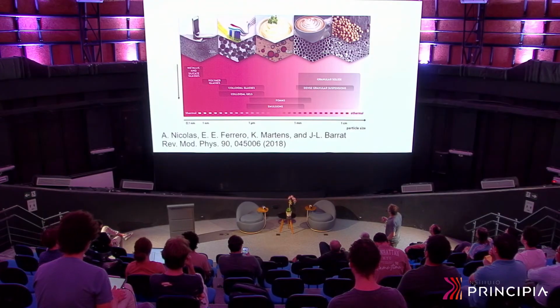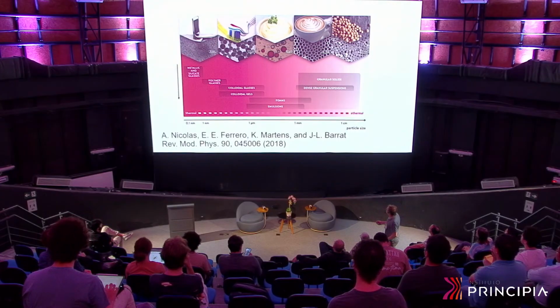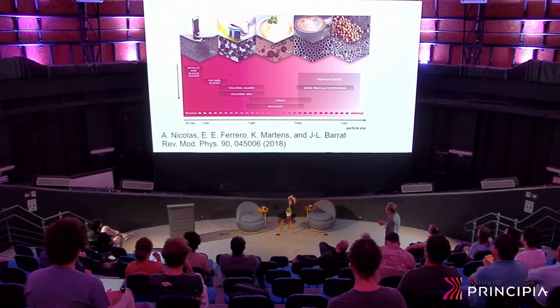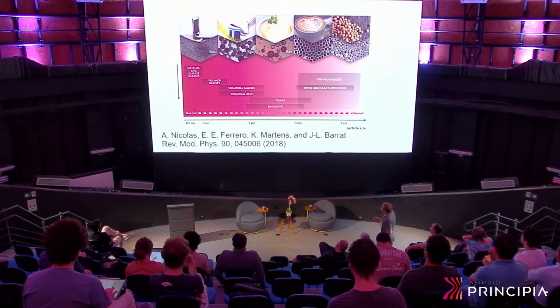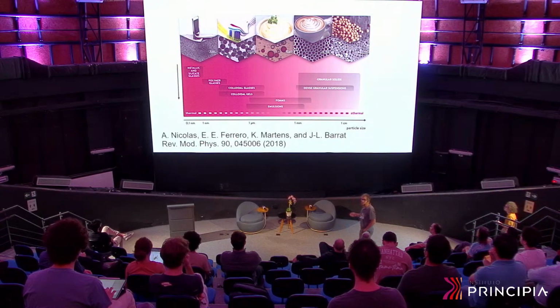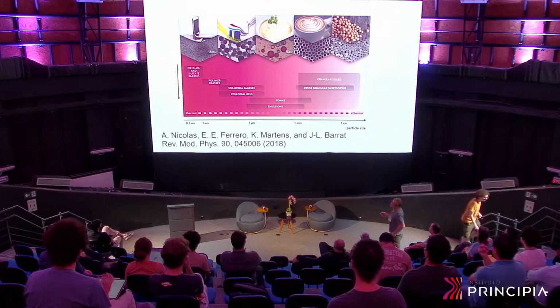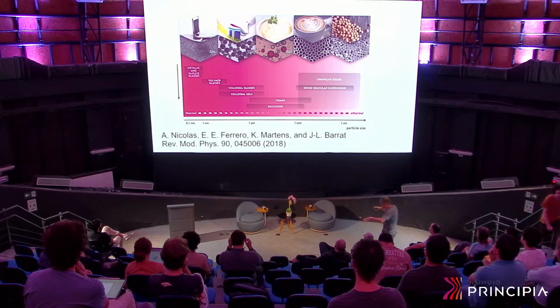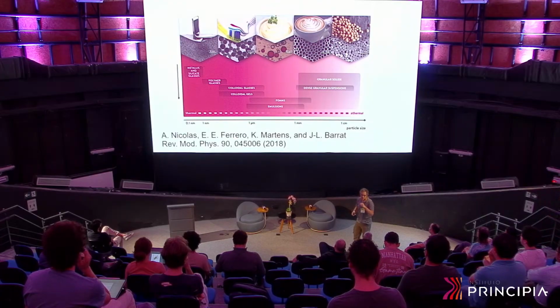And the other motivation to put this slide here is to indicate that the effect of the grain size on the behavior of this material is that thermal fluctuations have very different effects along this line. Because you have to compare the thermal energy, kT, with a typical energy here that will probably be, if this is just a pile of grains on the table, the potential energy of moving a grain a distance of a radius, typically.